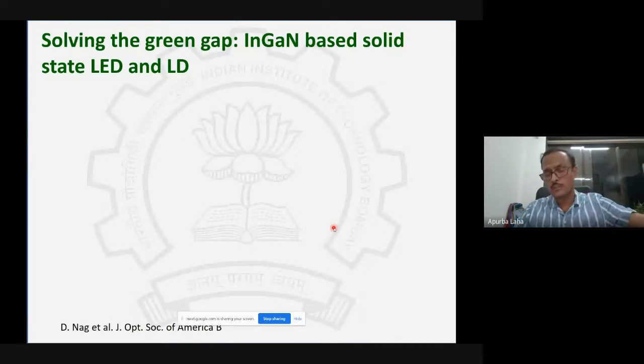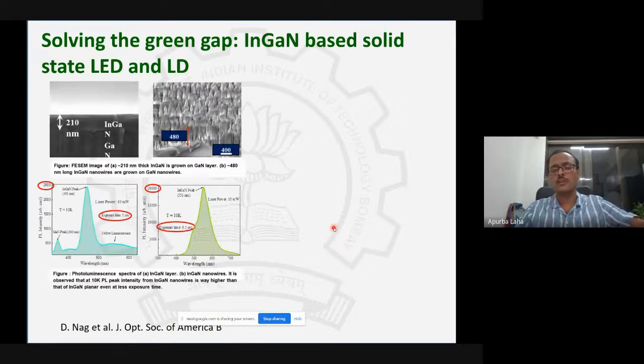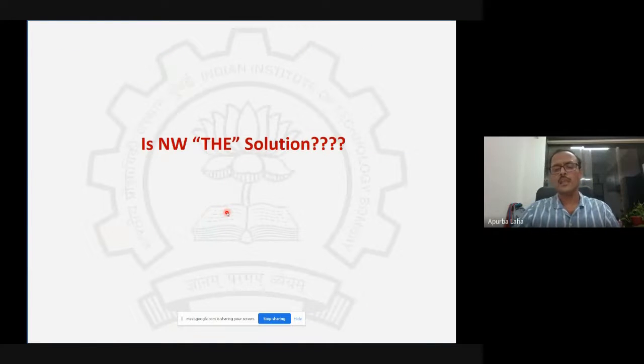Now, in the previous one, I showed you the aluminum, and here I'm talking about indium gallium nitride. As I said, we are working on the green LEDs and laser diodes. Here is an example where you see the high indium incorporation, which in turn gives emissions in the range of 500 to 600 nanometers with the same nanowire based indium gallium nitride structures. And now the final question comes: is the nanowire a solution? At this point, it is still very challenging, because when you are talking about commercial viability, it is far below the planar structure, because the efficiency and overall light emission is still significantly lower than the planar structures. So people are working on it, we are working on it, so hopefully we'll have some solution in the near future.